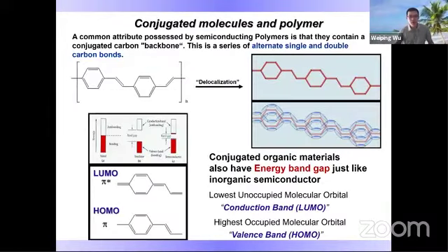These polymer and organic materials have been developed based on the principle of conjugated bonds of carbons. These conjugated structures have the characteristic of delocalization of charge carriers. Therefore, similar to inorganic semiconductors like silicon, these organic materials can form an energy gap, just like inorganic semiconductors. In these organic functional materials, we call them the HOMO and LUMO levels, corresponding to the valence band and the conduction band.